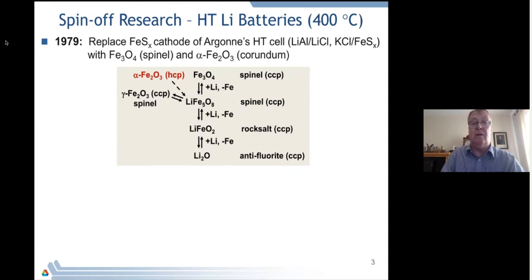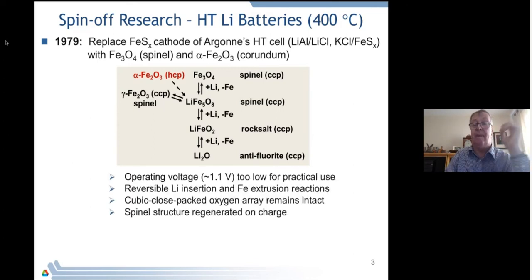We looked at two iron oxides, Fe3O4 and alpha Fe2O3, and discovered that these materials operated by a beautiful lithium insertion, iron extrusion reaction. Unfortunately, the operating voltage of these systems was too low for practical use.